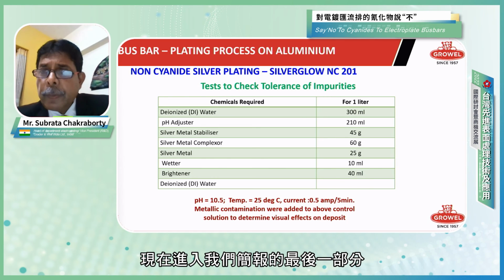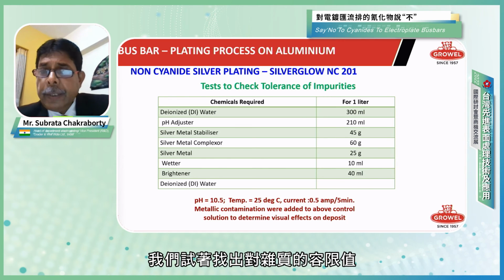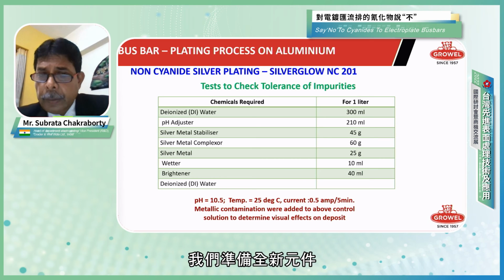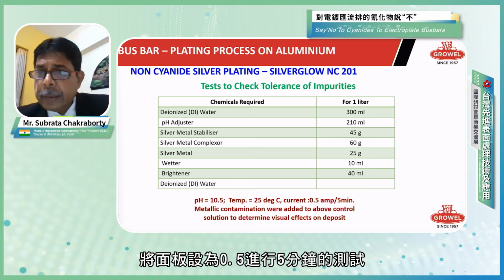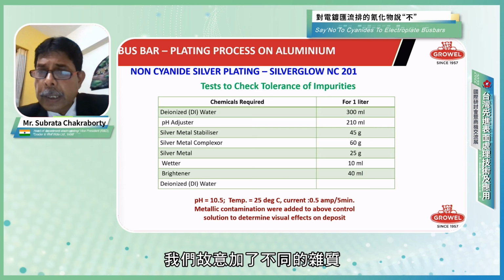Moving towards the last part of our presentation, we tried to figure out the tolerance to impurities. We prepared a fresh bath and checked the panels at 0.5 amp for 5 minutes in the Hull cell test, deliberately adding different impurities.